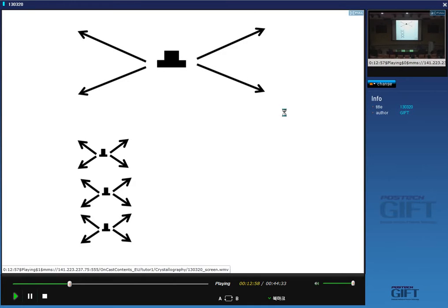So if you have an array of dislocations, then the energy per unit length of the dislocation line is smaller than if you have an isolated dislocation. And this, of course, is exactly the reason why when you heat treat a material containing dislocations, they will try to arrange themselves into walls, into sub-boundaries with small misorientations. So when you anneal a material, the dislocations will try to arrange themselves in such a way that the regions of compression and tension are compensating.